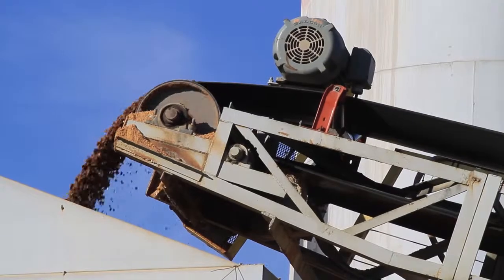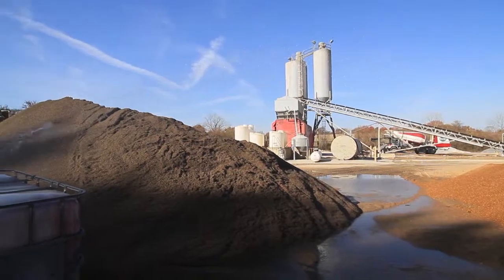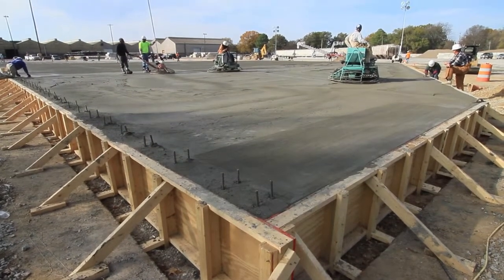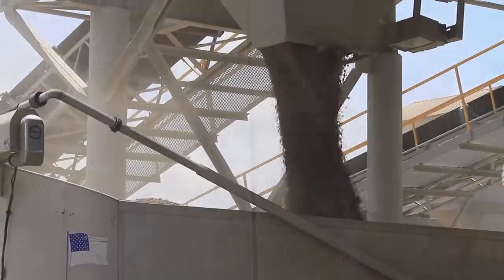It did require a little more vibration on the sand bin to get the pre-soaked lightweight aggregate to fall into the weigh hopper, but other than that, there were no issues with the lightweight material. The contractor placing the concrete was also pleased with the performance of the material — the concrete placed well. The subcontractor who did the sawing of the control joints commented he was able to do the saw cuts in less time than it would have taken without the internal curing.